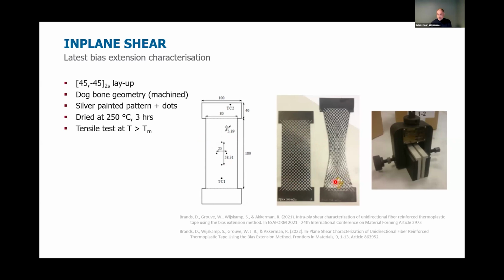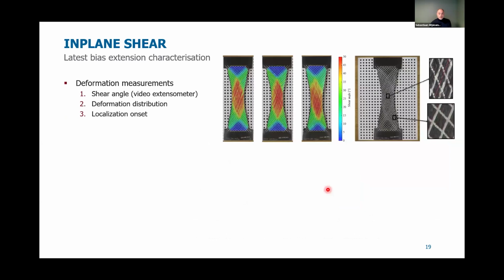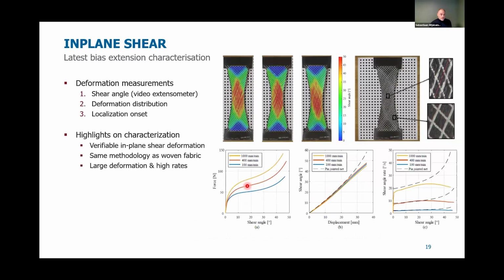And we perform these tests in a universal tensile testing machine at temperatures above the melting temperature, or after cooling down from the melting temperature to a temperature above the recrystallization temperature. So as said, the shear angle can be measured by the video extensometer. Post-mortem analysis could be done using this crosshatch and the video picture image analysis. And zooming in, in some cases you could see also the onset of localization, but only at very, very high deformations.